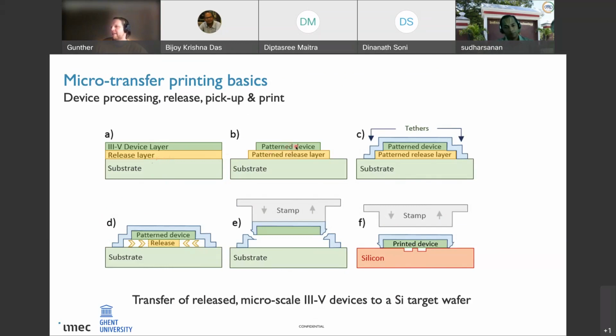So what you do next is you pattern your III-V device. You also pattern the release layer, and then you encapsulate it with a dielectric material. And that dielectric material is designed such that on one hand, it anchors the patterned device to the substrate through these so-called tethers here. But there are also openings in that encapsulation layer such that you can selectively etch away the release layer here, such that you're left with the thin film devices here attached to the substrate by these tethers.